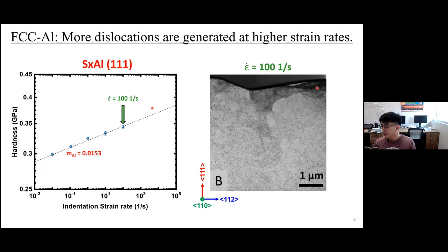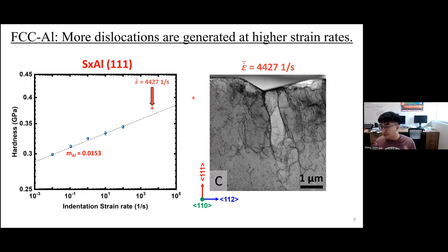To investigate further, we used FIB liftout to observe microstructure evolution at different strain rates. For indents deformed at lower strain rate (0.01), we found a diffuse dislocation structure. With four orders of magnitude increase in strain rate, dislocation activity increases and some subgrains on both sides start to form, though most dislocation activity remains confined within the plastic zone. More interestingly, with one order of magnitude increase from strain rate 100 to 1000, something totally different happens: more dislocation generation, larger subgrains, and a dislocation cell structure forms, probably due to increased local dislocation densities.